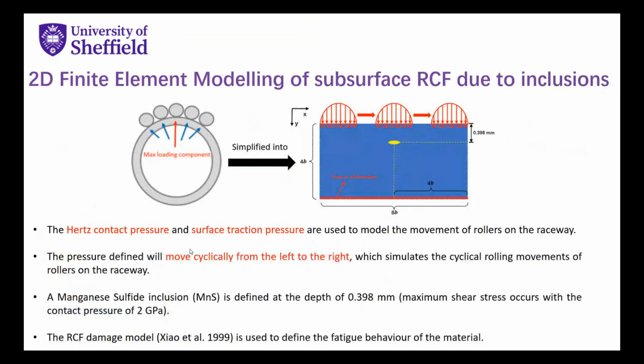Then I'm going to introduce my FE part. It's a two-dimensional FE modeling of the subsurface rolling contact fatigue due to inclusions. In my FE modeling, I simplified the contact between the roller and the raceway into this rectangular model here. As you can see, I did not have the rollers in this model. I use the Hertz contact pressure and the surface traction pressure to simulate the movement of the rollers on the raceway. And these pressures will move cyclically from the left to the right, which simulates the cyclical rolling movement of the rollers on the raceway.